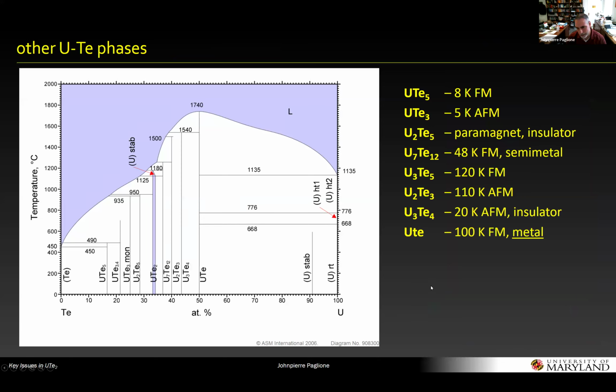And then just a word about uranium and tellurium. There are many phases, and if you just look at the phase diagram of tellurium to uranium, you can see that UTe2 is this line compound, well, not a line compound, but it has a width of formation almost to the melting point. And there are nearby phases, so you can easily get other phases in a lot of these growths, and you have to be careful. It's been reported in salt flux crystals that there are intergrowths, it seems, at least on the surface, of some of the other phases.